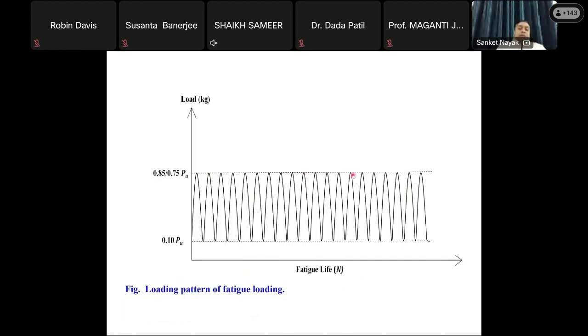So this is the loading protocol. Here PU stands for the ultimate flexural load, and for the fatigue, the minimum load is 10% of this ultimate load. It has been tested with respect to two stress levels: one is 0.85 of the ultimate load and another is 0.75 of the ultimate load. This is the loading profile for the fatigue loading, with repeated fatigue loading applied.